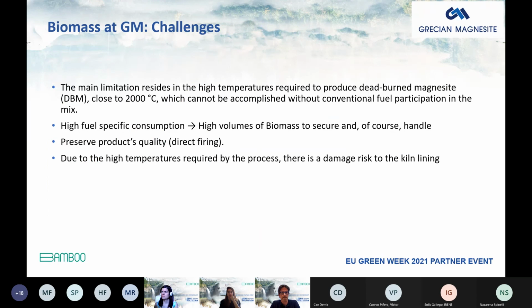The biomass used at Grecian Magnesite has to meet several challenges. There is, of course, a main limitation here, which has to be stressed. This main limitation resides in the high temperatures required to produce dead burnt magnesite, which are close to 2000 degrees Celsius. This cannot, unfortunately, be accomplished without conventional fuel participation in the mix.